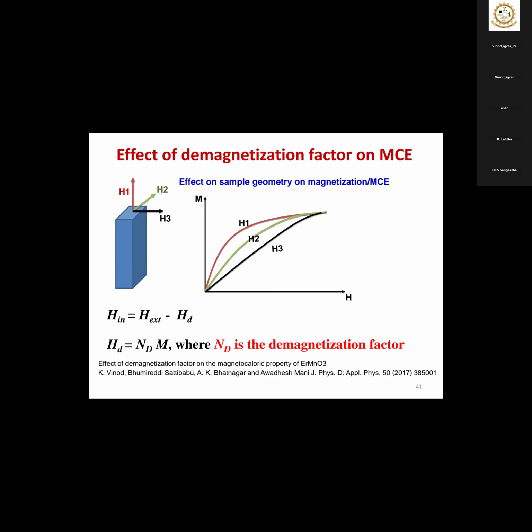This part also, I will just quickly go through. These are some additional work: sample geometry dependence. The same sample, depending on which direction you are applying the magnetic field, will give a different magnetic moment. It is called the demagnetizing factor, depending on the geometry. When you apply the magnetic field to a material, depending on the geometry, it will have internal polarization. That is called demagnetization. Because of that, the actual internal field inside the sample will be different.